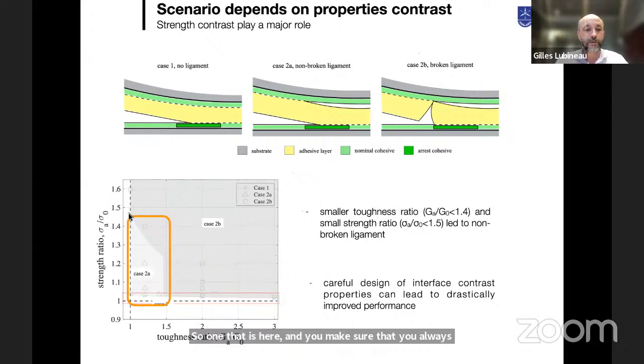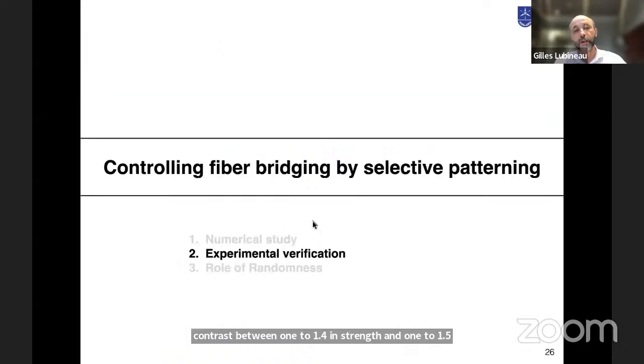And then you can see that there is a design space here in which you need to optimize your contrast between 1 to 1.4 in strength and 1 to 1.5 in toughness. So you really create these ligaments. And then you can see if you can do this experimentally. So this is really what is interesting to us.